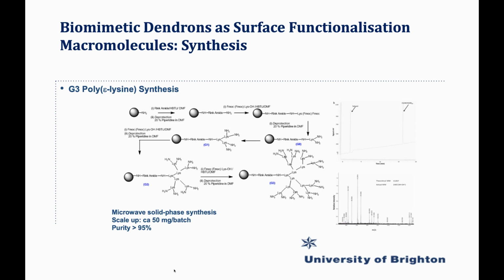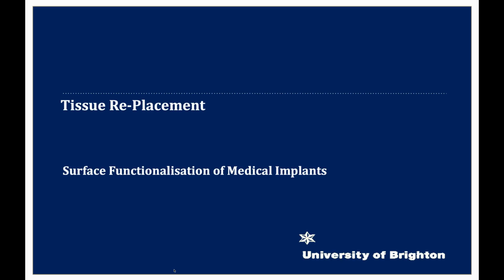The way we do it is through an adopted and adapted peptide synthesis, where with a solid phase, solid resin support, we produce hyperbranched molecules. These hyperbranched molecules expose amino groups, typically 16 amino groups, to which we then attach the bioligands recognized by the cell.